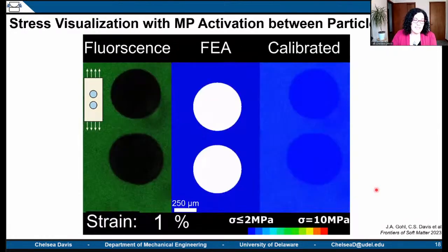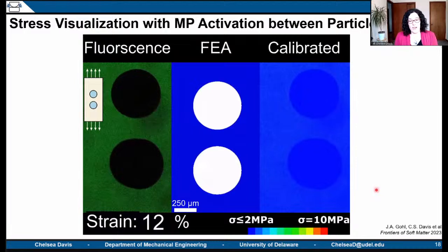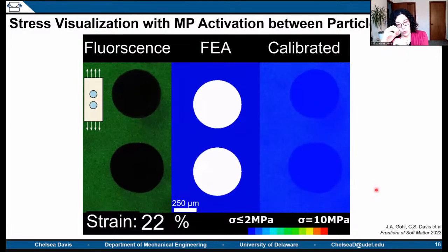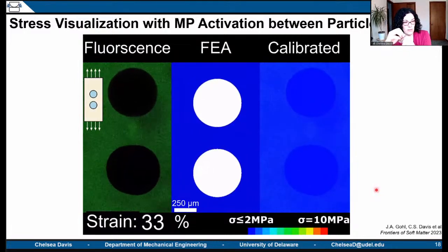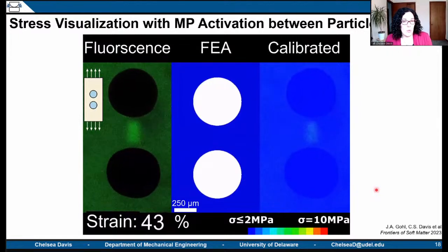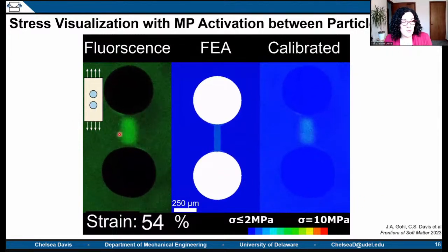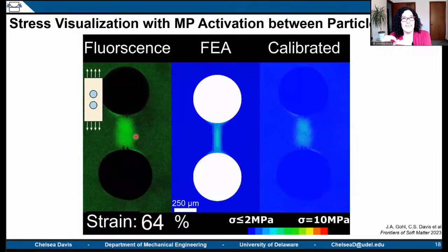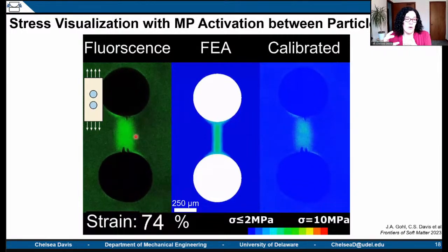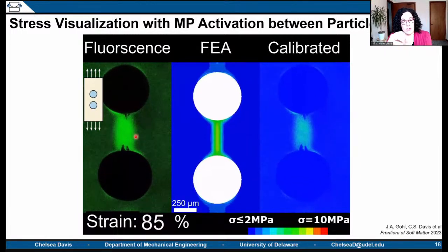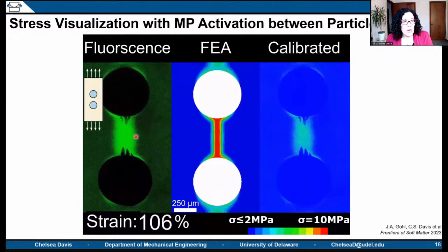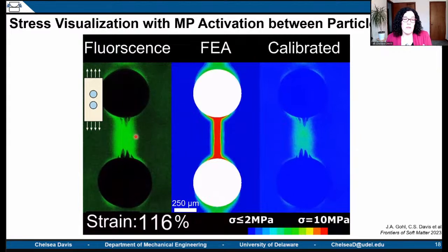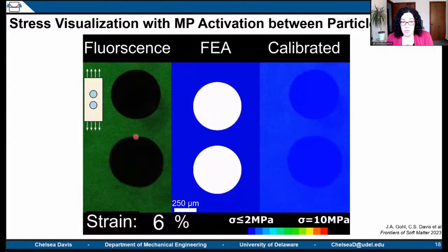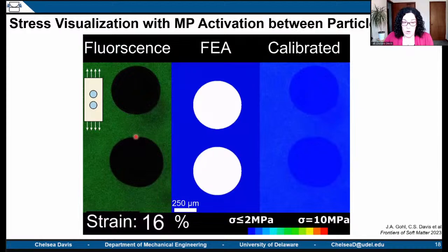But now we can take that same calibration, and if we take two particles that start at one radius of separation and start pulling them apart, what you'll observe is we get this really exciting crosstalk or concentrated stress event where you have these two particles really close to each other. And this starts to become important in particle reinforced elastomers, like the tires that you drove to work on.